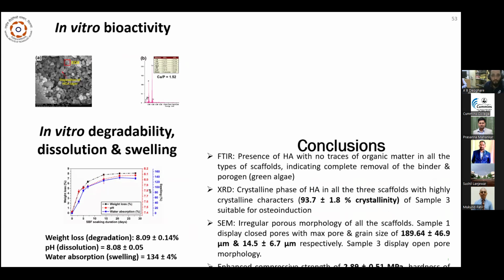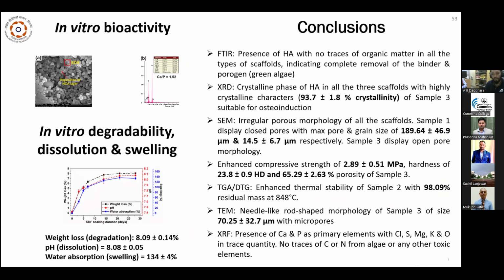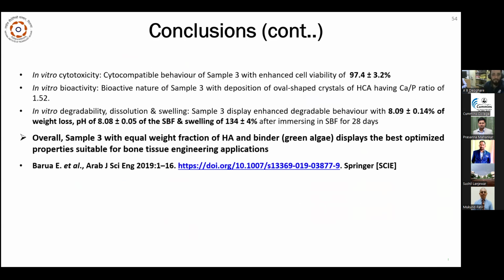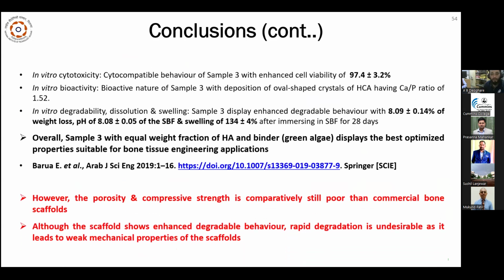Then an in vitro bioactivity test is performed to check whether apatite is formed or not, where it shows a calcium phosphate ratio of 1.52. From the analysis, it can be concluded that sample 3 shows better results compared to the other samples. So from the above analysis, it can be seen that although it is best suited for bone tissue engineering applications, there are some limitations, which are lower porosity and compressive strength compared to a commercial bone scaffold.